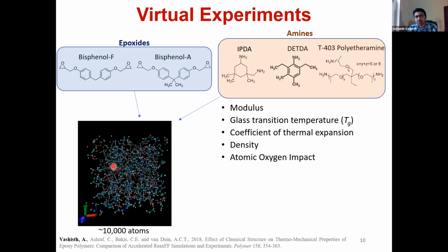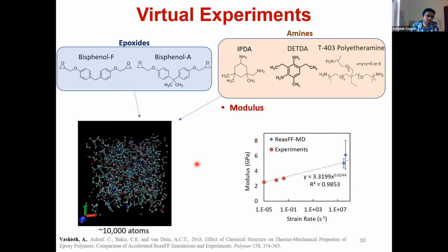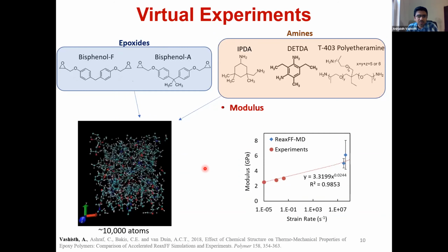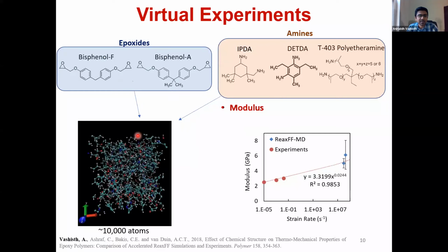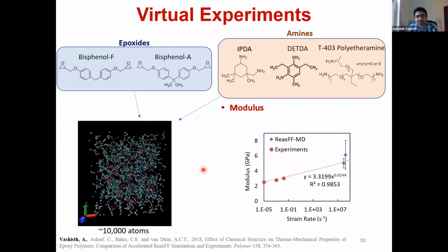And on this virtual polymer, you can do a bunch of experimental testing. You can do modulus, TG, coefficient of thermal expansion, density, atomic oxygen impact. So I'll show you one simulation of modulus here, where we examined the tensile testing. We did a virtual tensile test on this polymer.